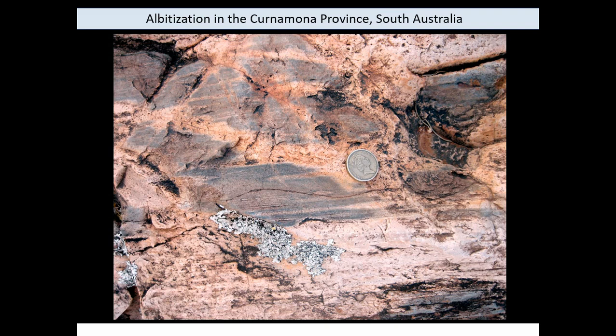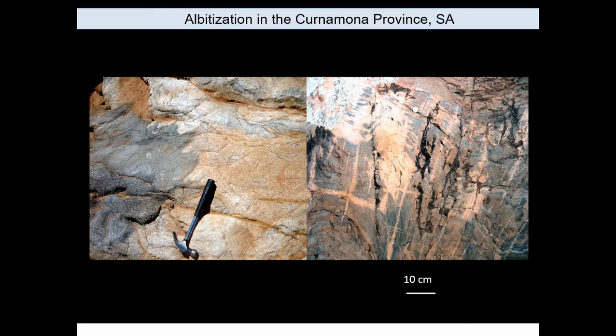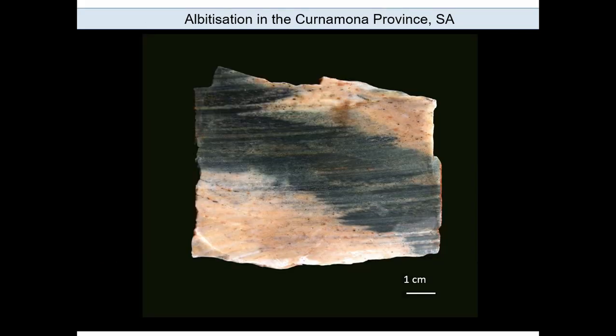Look at the interfaces. There's a pinkish one, that's albite, and it's almost pure albite. The gray one, in this case, is a potassium feldspar, also containing a lot of other elements. But in the field, when you see interfaces, there's an indication maybe some kind of replacement reaction has taken place. There are just a couple more images to show the scale of the interfaces that we were observing. This was a hand specimen that I took, and I actually did work across those interfaces, which on a nanoscale are actually very sharp between the albite and the K feldspar.